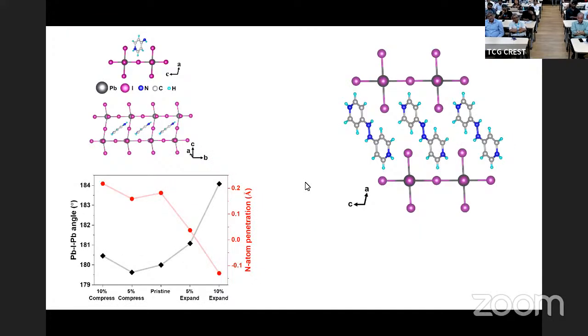The reason we get this 180 degrees, which actually is at the center of both the band gap being lowered and excitonic binding energy being lowered, is because, as I told you, this iodine wants to enjoy 2 hydrogen bonding, one with this one and one with that one. In order to enjoy this hydrogen bonding, this head of the organic molecule has to penetrate into this inorganic layer defined by the iodine layer.